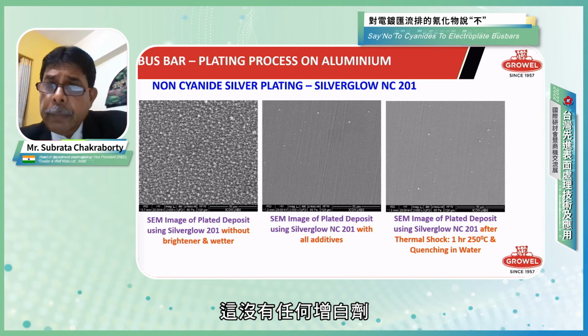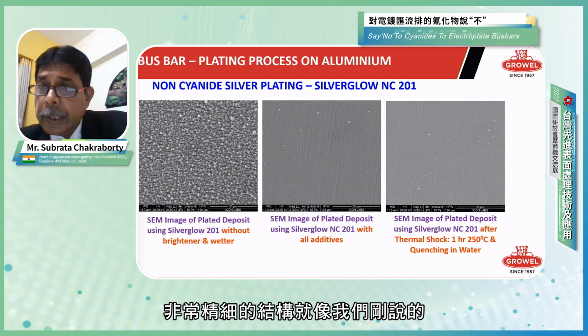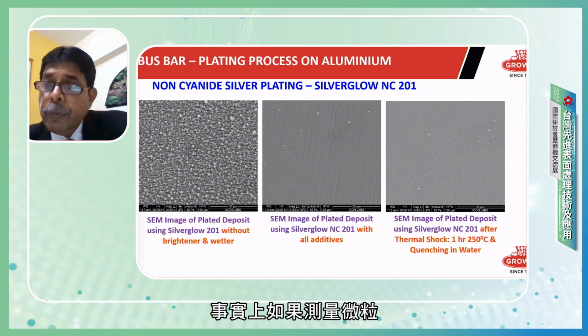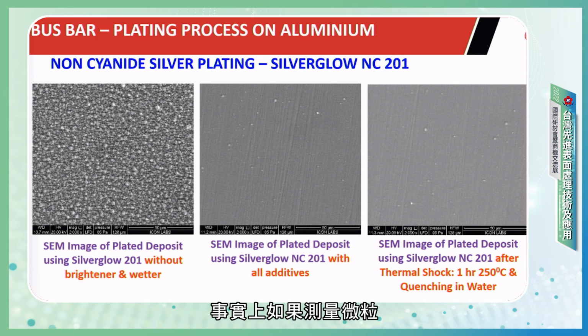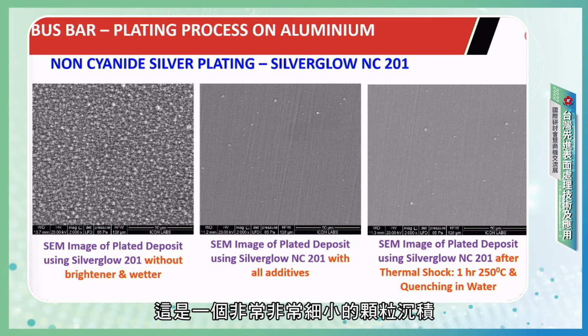This is without any brightening agents, and with the brighteners we get a very fine and compact grain structure, as we discussed. If we measure the grains, it varies between 450 to 700 angstrom, as against cyanide silver of more than 40,000. So it's a very, very fine grain deposit.